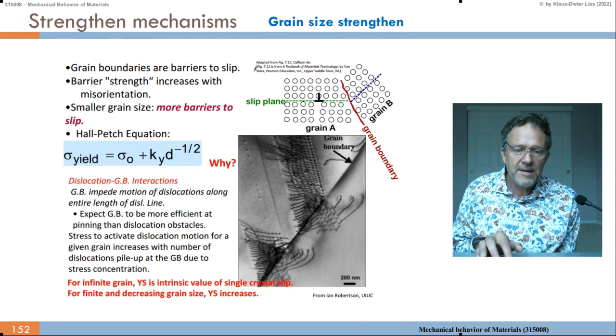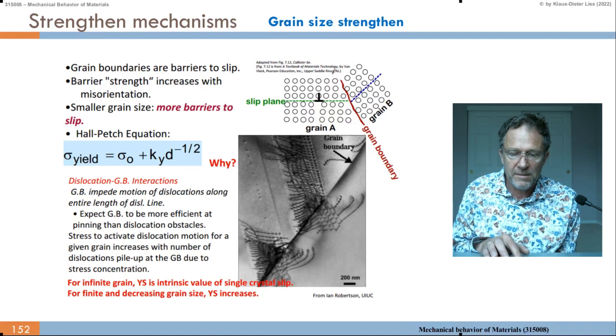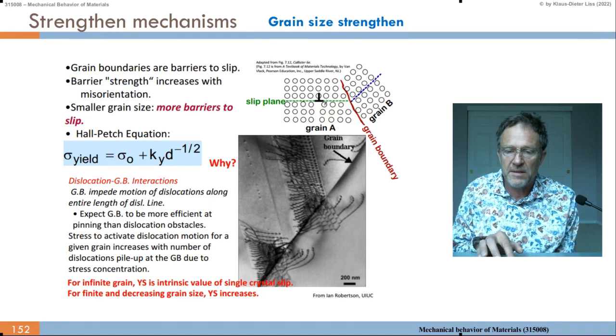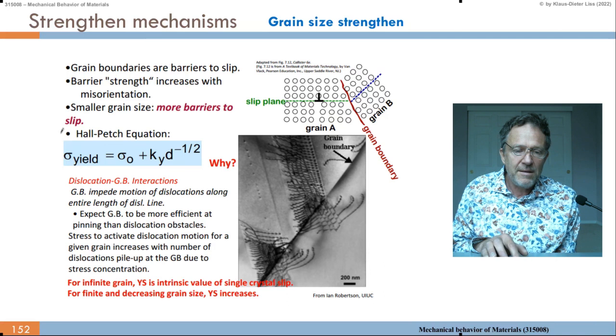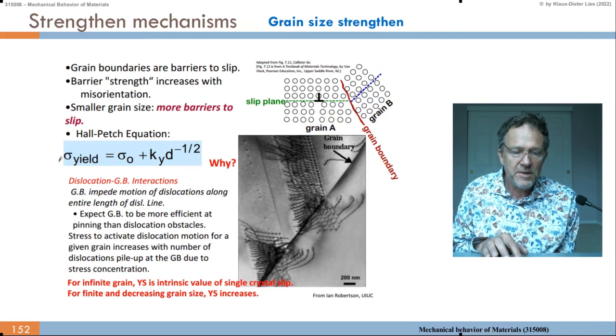So the grain boundaries are barriers to the slip, and the barrier strength increases with the misorientation. This also makes sense. If there's a big misorientation angle, then it's difficult to induce a dislocation on the other side. And of course, as I've shown, with smaller grain size there are more barriers to slip, which leads to the whole Hall-Petch equation. So the yield strength equals sigma 0 plus ky divided by square root of D.